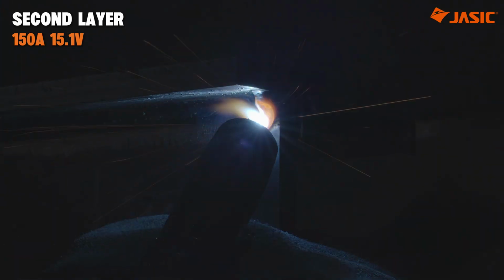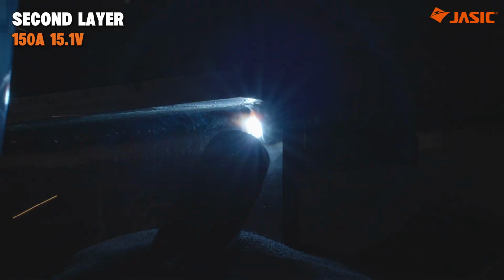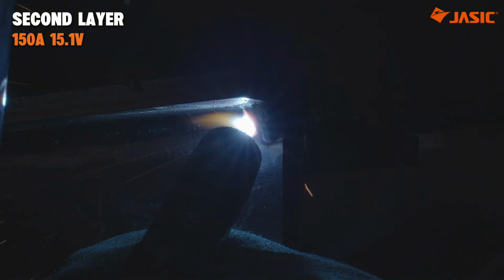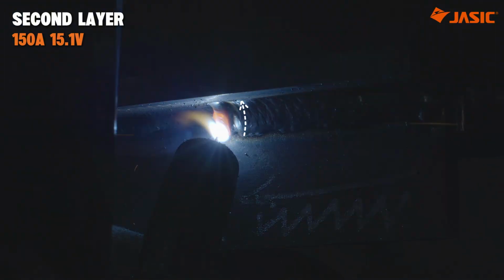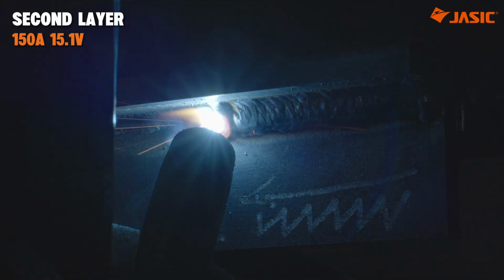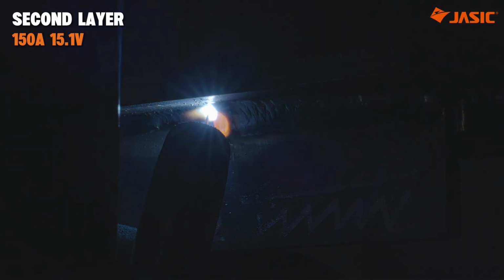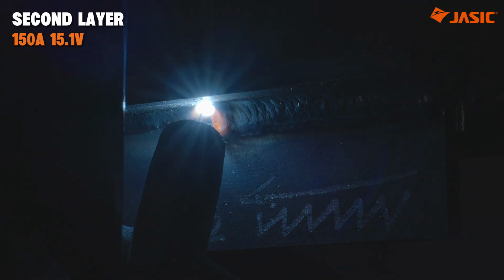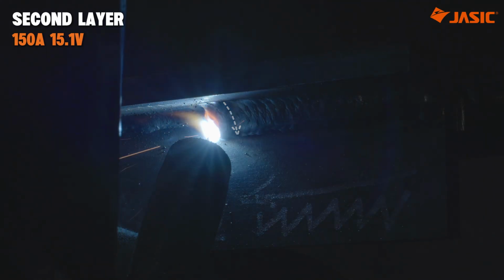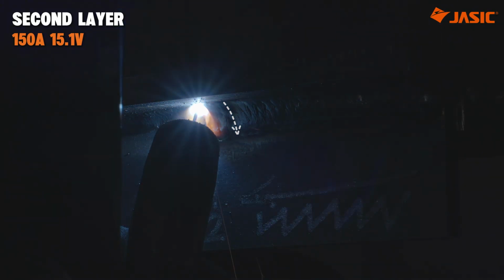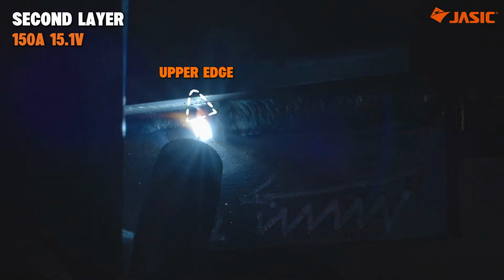Second layer, angled zigzag for the cover pass. The zigzag movement should be angled rather than simply moving from side to side. When you move toward the upper side of the joint, as the wire moves across the center of the weld, use it to carry the molten pool toward the upper side of the joint, making sure the upper edge gets proper fusion. When moving toward the lower side, move forward slightly as you go. Each movement should reach the upper edge of the molten pool.